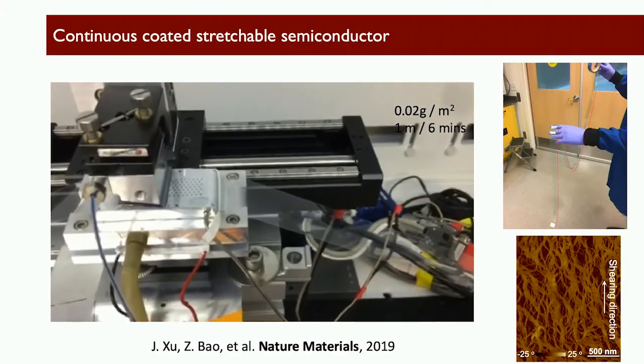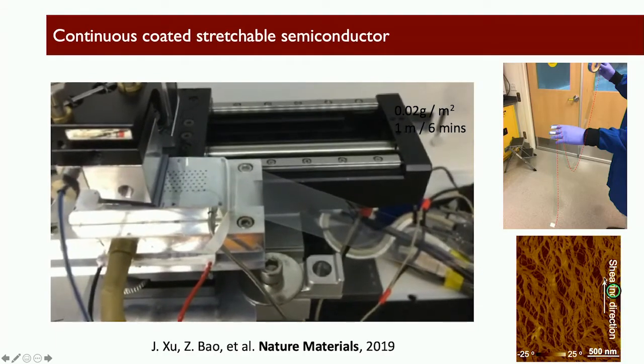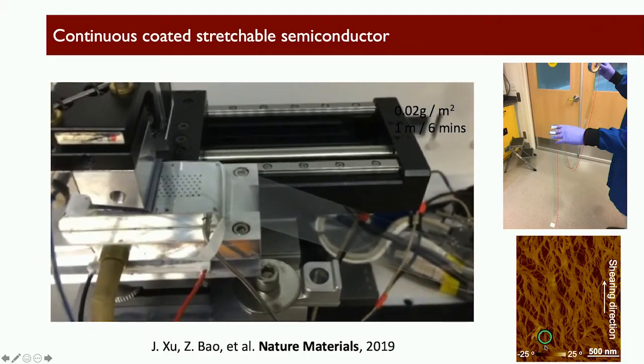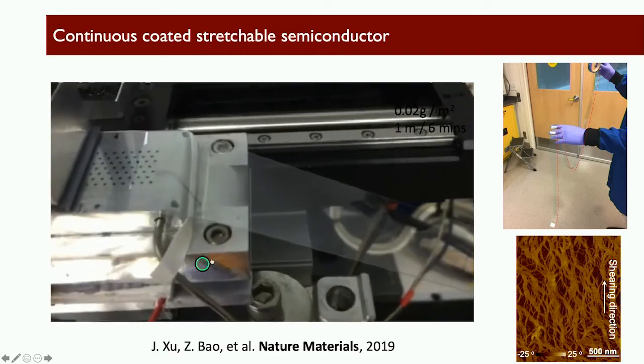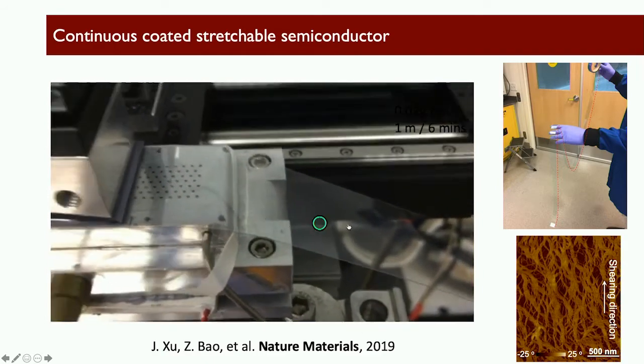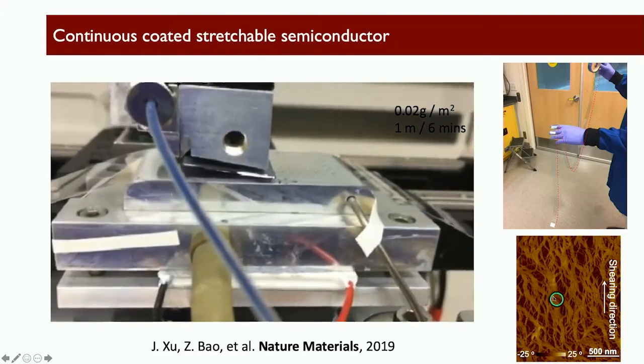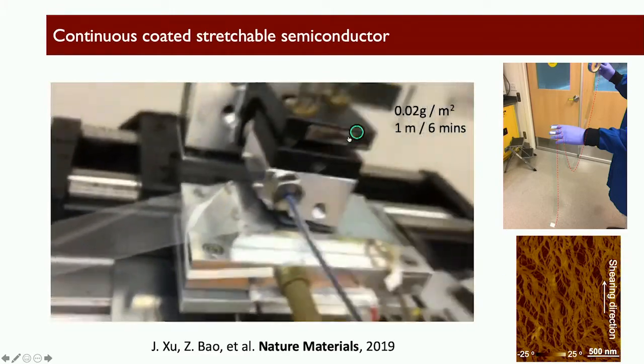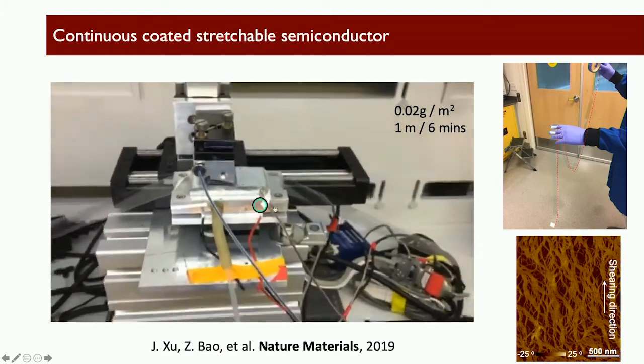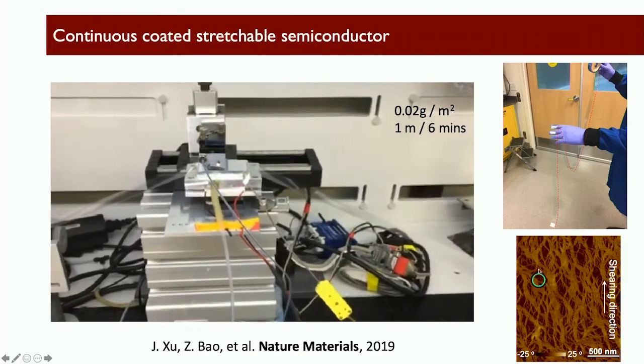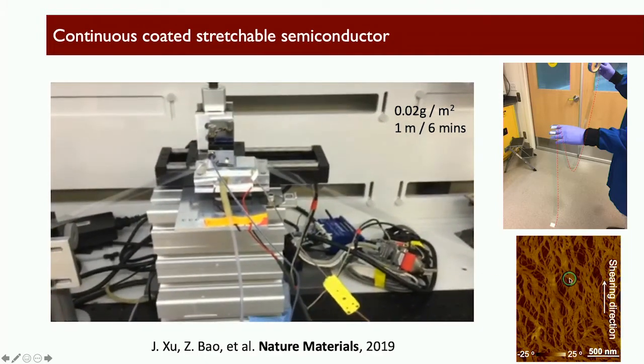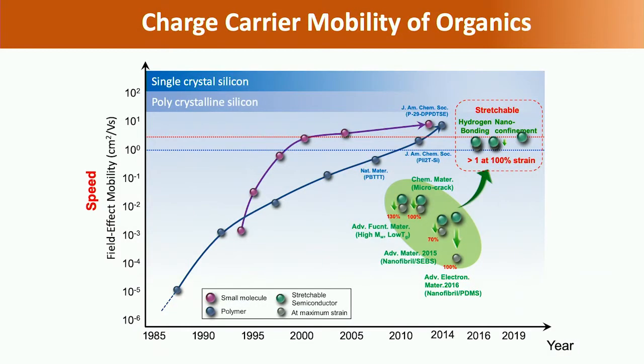And these kinds of semiconductor can even have a boost in the charge transport if the nanostructure in these materials can be aligned during the coating. So this is actually how we align these semiconductor nano-confined fibers. And through the coating process, we actually align the fibers in the polymer semiconductor. And this gives a boost in the mobility to the order of 7 to 8 centimeter squared per volt per second.